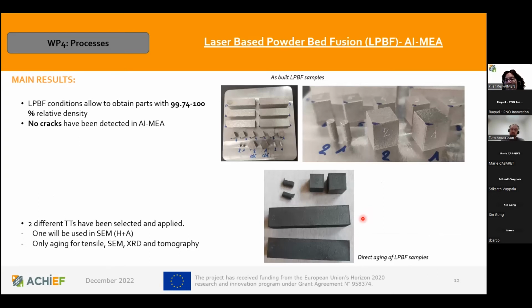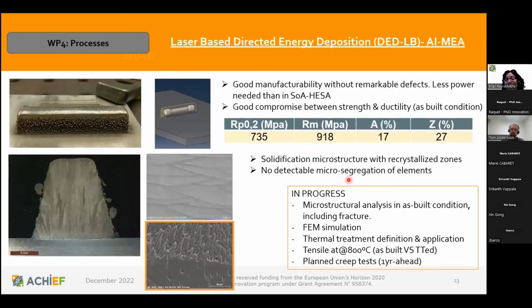If we move to this alloy, you can see here that the quality is completely different. With PBF, we reach almost 100% relative density, and no cracks were detected with this material. Now we are performing some thermal treatment on this material in order to promote a multi-phase microstructure and increase the resistance of this Al-MEA material. For DED, what happened? As I mentioned, the quality has nothing to do with the first one, so we don't detect cracks or porosity. We were able to deposit some coupons here and extract some tensile specimens. As you can see, the properties at room temperature at least are very good, with a very good compromise between strength and ductility.